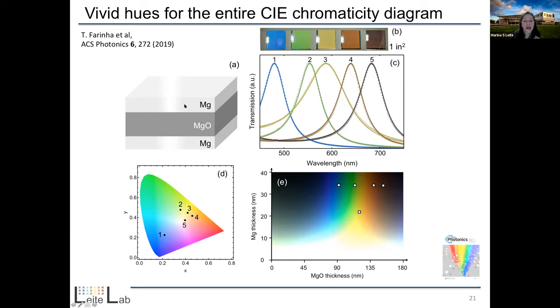Second of all, what happens here is that depending on the thickness of this MgO layer, we have a Fabry-Perot resonance effect that essentially allows us to engineer, as a function of wavelength, how much transmission we have at a certain point. So basically, depending on the thickness of this MgO layer, we can make color pixels in different hues. And here I'm showing to you a photograph in transmission mode. Basically, we use the light source in the back, so that's why you see these very bright spots here.